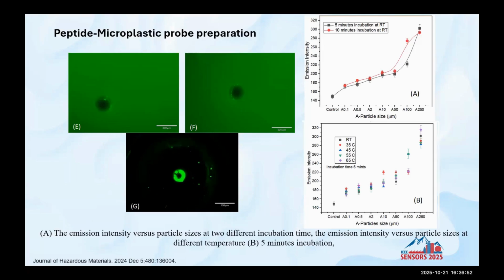We did a test to find out the optimal incubation time and temperature needed for optimized interaction between these two, and also what would be the best time of incubation. With this optimized, we figured out that even at room temperature, just 5 minutes is enough to mix these two together and find the best optimum interaction, and we see them under the microscope.